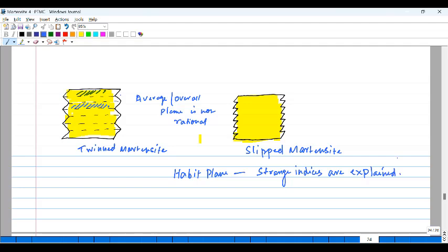So in summary, basically what we have in this Martensite transformation in terms of the mechanism is an invariant plane strain P1, which is combined with another invariant plane strain P2, both of which are shear, which generate the right crystal structure. But the shape is wrong.